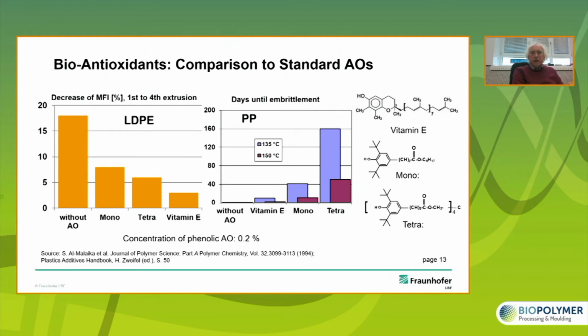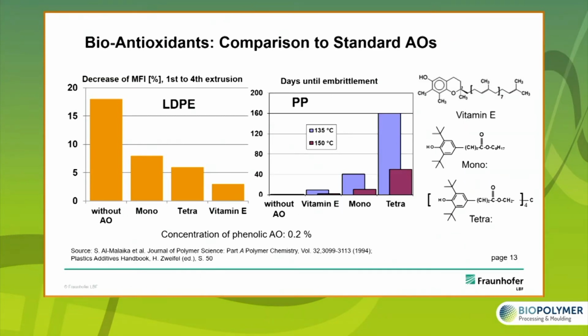With an addition of normal antioxidants we call mono or tetra, the degradation will be reduced to 5 to 10% only. Then adding vitamin E in the same concentration, the degradation is even lower, as you can see on the left-hand side. That's to say, vitamin E, in this example LDPE, is a very good stabilizer, which performs even better than the normal antioxidants.